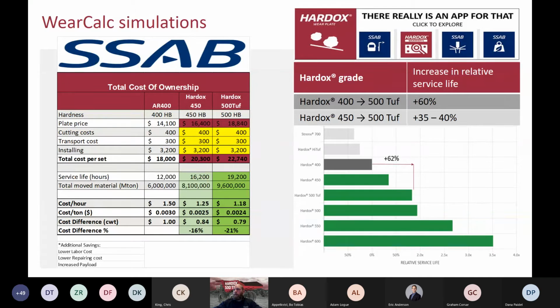Earlier we looked at the relative wear life, which came from our Wear Calc simulation. Basically what we're saying is you go from an AR 400 or Hardox 400 up to the Hardox 500 Tough. For this, we can see a cost difference where you can have a savings of around 16% going from an AR 400 to Hardox 450. Or if you go up to a Hardox 500 Tough, you can see a cost difference of around 21%. So the cost per hour and the cost per ton are reduced by the service life increase of the steel.